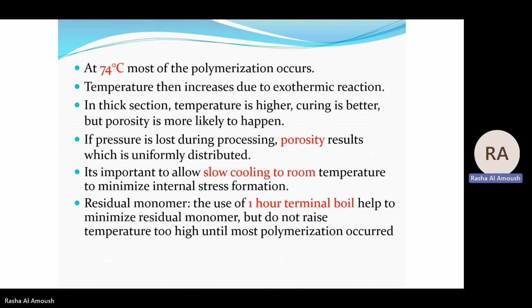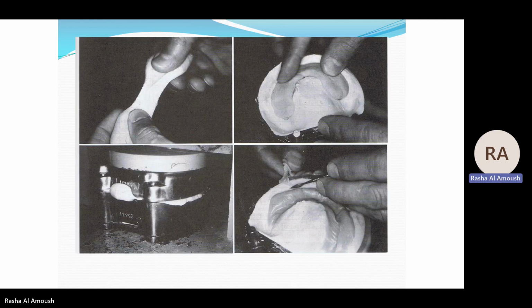the boiling temperature, we know that the boiling temperature for the monomer methyl methacrylate is 100.8, so make sure not to exceed the temperature or to reach the boiling temperature of the residual monomer, otherwise we will have some porosity, especially gaseous porosity.